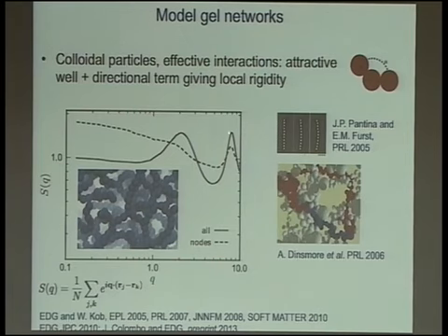And so this is measuring the correlation between particle positions. You have a peak that corresponds to particles that are nearest neighbors within the attraction well, so the bonds actually between the particles. And then the interesting thing is that, this is a wave vector expressed in terms of our unit length in the simulation, which is the particle diameter, you have an excess of spatial correlation also at smaller wave vector. And this is what basically captures the structure of the network and the presence of long-range correlation that are related to the fact that it's a spanning network of particles. Here we have separated the contribution that comes from all the particles, and this dashed line is the contribution that comes just from the nodes of the network.